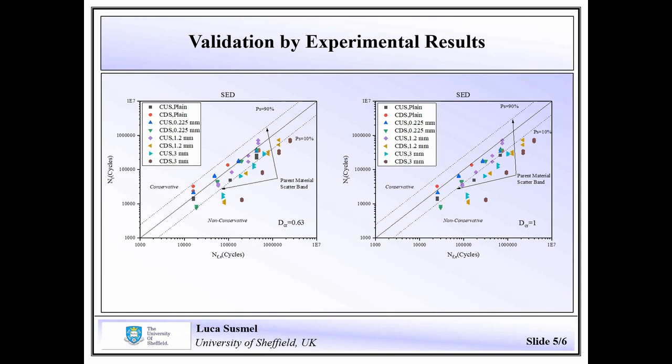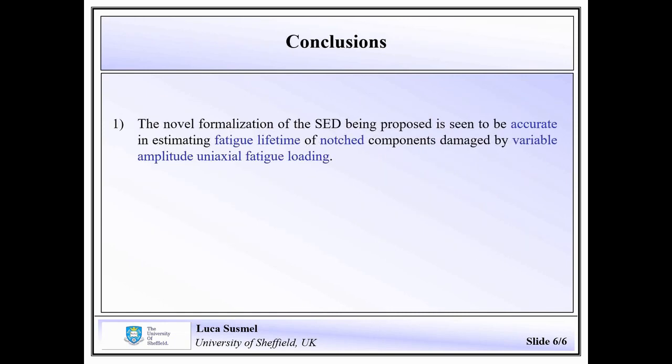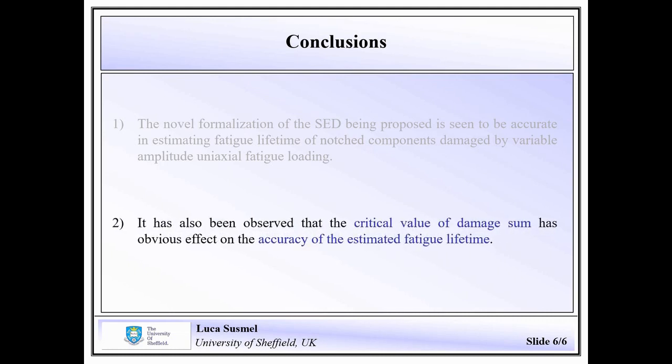In conclusion, we can say that the proposed formulation of the strain energy density approach is capable of estimating fatigue lifetime of notched components subjected to variable amplitude uniaxial fatigue loading. And as expected, this formulation of the SED is seen to be sensitive to the critical value which is used to estimate failure in terms of total damage sum.